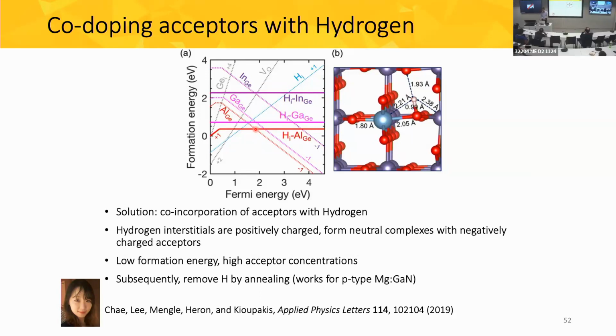Great question. Yes. So how do we study defects and complexes, and where do we stop looking at combinations? In this case, we start from the simpler complexes first, or individual defects or defect pairs. The reason why you may not form larger clusters has to do with the entropy. So even though energetically defects may like to cluster, there's a much higher entropy in dispersing them all over your sample. So typically in these complexes, the entropy is enough to dissolve them across the material. We need to keep, in principle, exploring higher orders. I think our safety net is the entropy, that at some point entropy wins and these complexes dissociate.